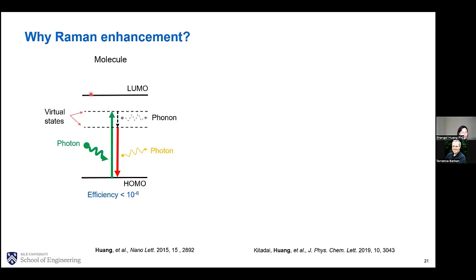But these molecules have discrete states. So typically, you can only excite the electrons from the HOMO level to a virtual state within these actual electronic states. So the virtual states are metastable. The efficiency of emitting photons from these virtual states is very, very small. So this results in a very low Raman intensity. So the efficiency is actually lower than 10 to the minus 6.